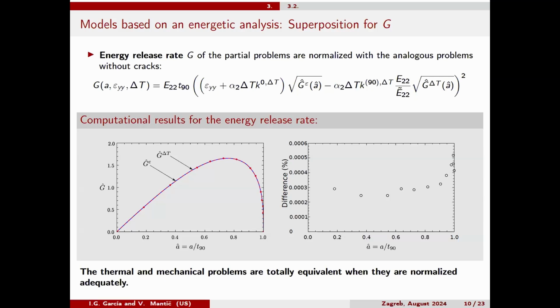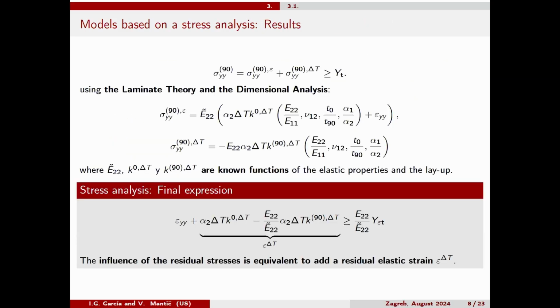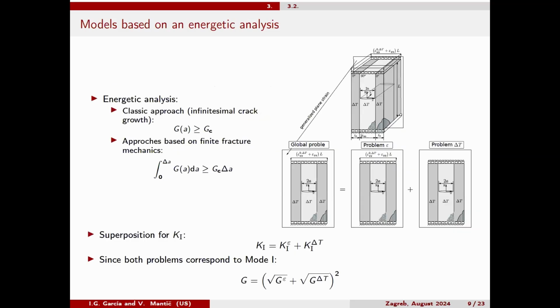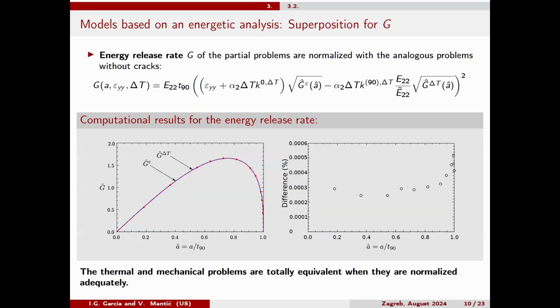We need G, the energy release rate, for each partial problem. And we did that with boundary element. We can do that with finite element also. But we did it with boundary element, and normalized the result for G with the stresses that we obtain for the corresponding problem in the stress analysis that we did before. With these stresses, what we obtain is that G is the same for the thermal and the mechanical problem. And this is very interesting, because it avoids us having to calculate a thermal problem. We obtained that numerically, but it was proved by Professor Mantic some months ago.